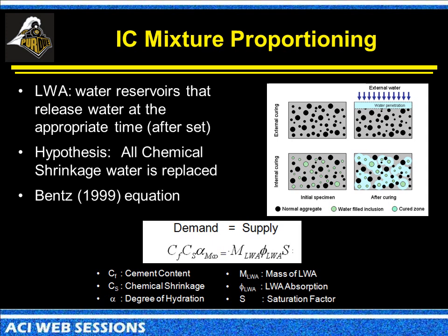So we're giving back about 90%, 92% of the water that goes into the system to supply the internal curing. The whole goal here is that the lightweight aggregate is going to release the water when it's needed to hydrate the system. One of the big benefits is that it's more distributed throughout the entire cross-section, so we're not just getting the benefit up at the top where the water might be. The hypothesis is that we're going to replace all the chemical shrinkage that's taking place.